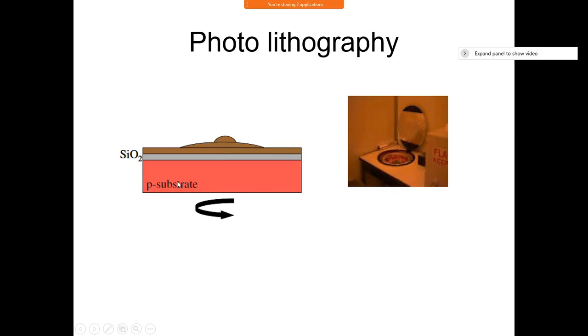I just put it on a chassis and make the chassis rotate at a very fast rate, maybe 1000 rpm or 1500 rpm. On top of that, you put small droplets of that PPR or NPR. When it is rotating at such a high speed, will it not spread evenly across the surface of your substrate?